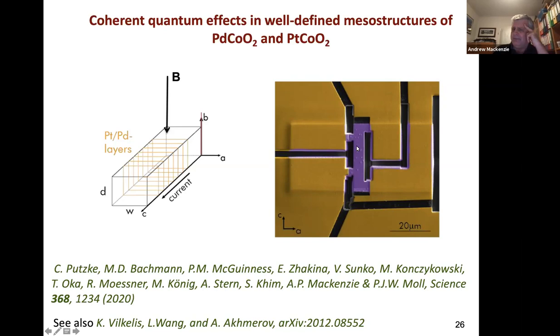So if we pass the current down, we are now putting two voltage probes along that track, which is long in the C direction. So we should be able to make a pretty accurate measurement of the C-axis resistance. And because we're doing it in a micro device, we have better chances of avoiding the cracking and various other tiresome things that happen to you when you try to measure C-axis resistivity in bulk devices. So we did it. We measured the C-axis resistivity.